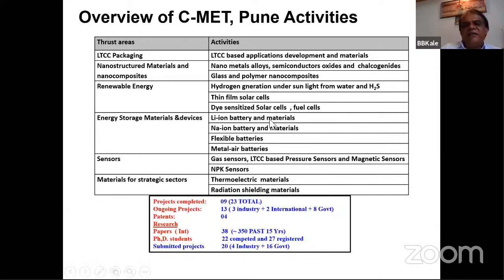Then metal air batteries. The lithium ion battery capacity is up to 130, 140 now, and in some cases 175. But metal air batteries can go up to 300 to 350, lithium air at least. So the capacity may be high, but it has some problems, like cycling. Initially we may get good capacity, but during cycling, oxidation takes place and we get a very drastic capacity fading. So this is a problem with metal air batteries.